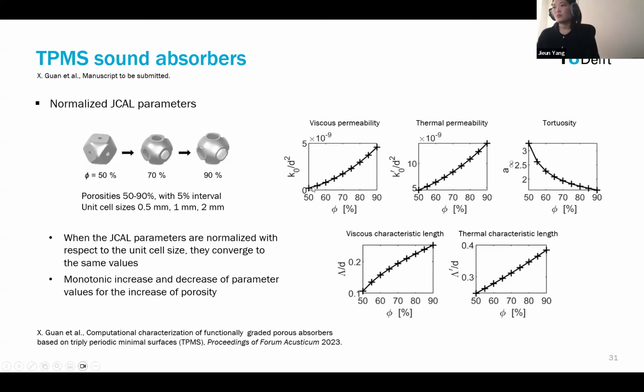And then they actually converged to the same value, and we published a little bit more detail on this aspect in this conference paper. So please check this conference paper if you are interested. And we can also see that there is a monotonic increase or decrease in the parameter values, including tortuosity, when the porosity increases. So it actually makes the optimization much easier, because if you have multiple values for different porosities, it could be quite fuzzy to get a clean optimization result.